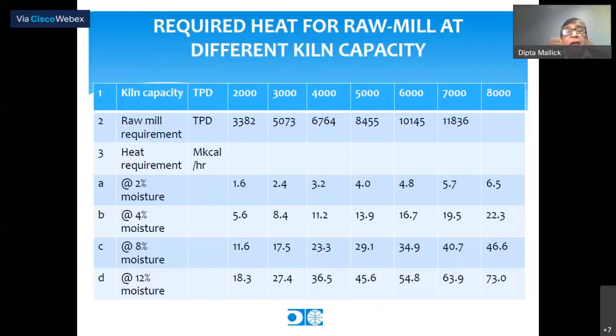In the raw meal, you need to dry the limestone to 1 to 1.5% of moisture, and normally we get limestone with higher moisture, 3%, 4%, 5%. So that means you have to put a sufficient amount of heat so that the moisture gets evaporated. So we have given a chart here that corresponding to, say, 2% moisture, what is the amount of heat that is required, corresponding to 4%, etc.